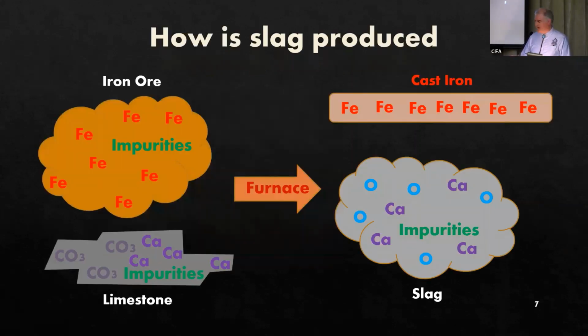So in this cartoon diagram, we can talk about how slag was produced. You notice that blob up in the upper left-hand corner. That symbolizes the iron ore. So you have iron, that's the Fe in there, and then you have impurities. The little green lettering signifies the impurities. Most of that iron is present as iron oxide, or iron atoms that are chemically bonded to oxygen atoms. To produce iron from the furnace, you have to separate the iron from the oxygen atoms.